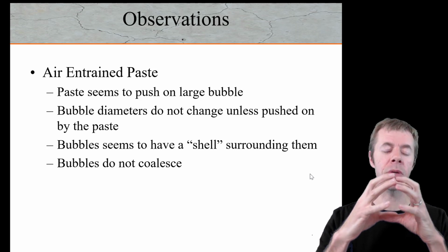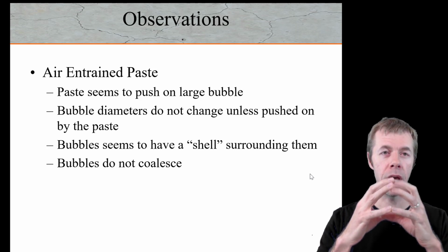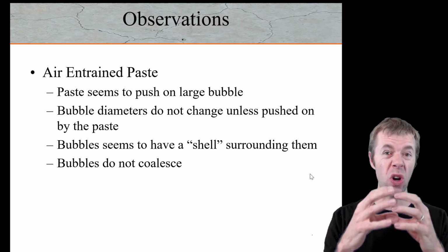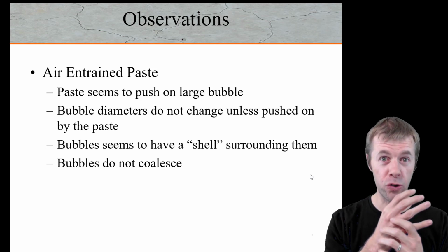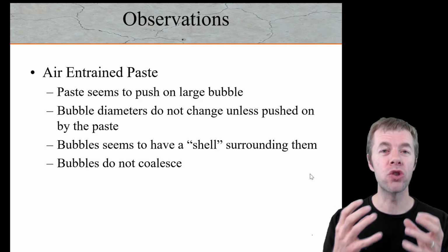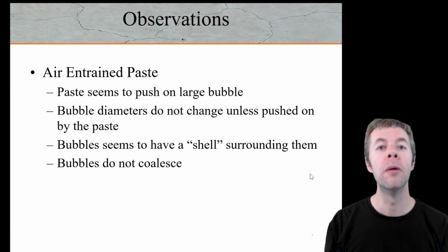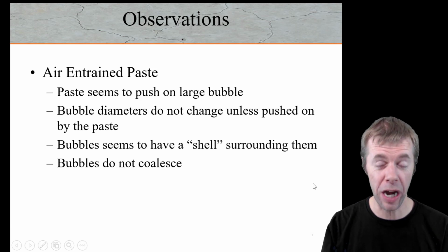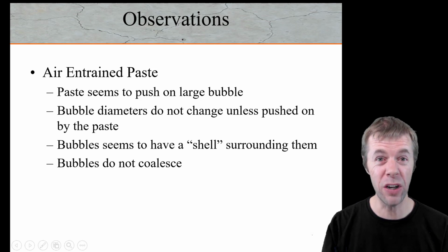The bubbles seem to have some kind of shell surrounding them, okay? Because we saw it crack and this bubble emerge from the inside, and the bubbles don't coalesce. They just kind of push each other around. And that was air-entrained cement paste. I know, awesome, right?